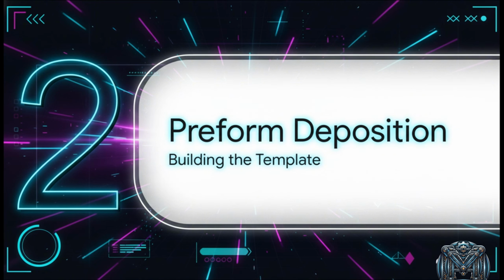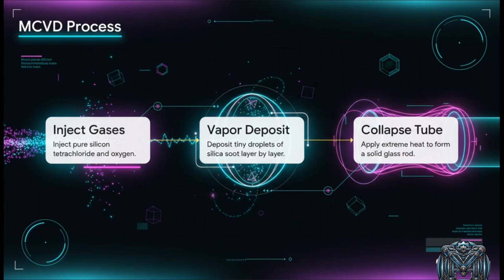Let's step into those sterile labs and see how we actually build the macro-scale foundation of our optical waveguide. We can't just draw a fiber from a random puddle of glass. We have to build a highly engineered template first, which we call a preform. We use the Modified Chemical Vapor Deposition, or MCVD process. By carefully injecting pure gases into a rotating, heated tube, we vapor deposit tiny droplets of silica soot, layer by microscopic layer. This lets us engineer the exact refractive index difference between the inner core, which carries the light, and the outer cladding, which traps the light inside. Finally, we hit it with extreme heat to collapse that tube into a solid, massive glass rod. That's our preform.